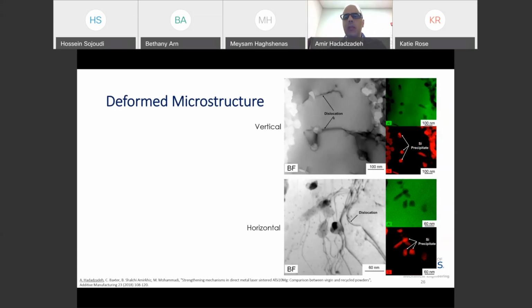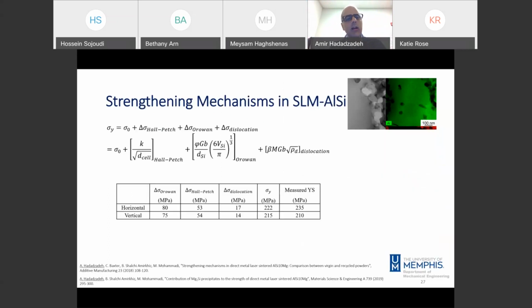I was also able to see the effect of silicon precipitates on the movement of dislocations. So here, for example, in this case, this dislocation is pinned by the silicon precipitates. This is a kind of classic image. Another case, a dislocation which is pinned by a silicon precipitate. If the dislocations are able to bypass the precipitates, like this case here, we see the effect of that. So this dislocation has gone toward the silicon precipitates after bypassing. And also there are some other dislocations that are still pinned by the precipitates. So precipitates are playing a role in the strengthening of the material because, again, they are hindering the motion of the dislocations.